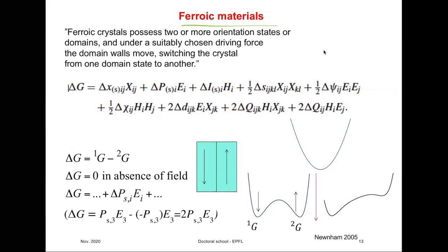However, its 90-degree domains, which are ferroelastic domains, are also at the same time ferroelectric. So it is a ferroelectric, ferroelastic material, but it has purely ferroelectric domains and ferroelectric-ferroelastic domains. It doesn't have purely ferroelastic domains. A material that is ferroelastic without having polarization is, for example, zirconium dioxide. You can learn about this from Newnham's book.